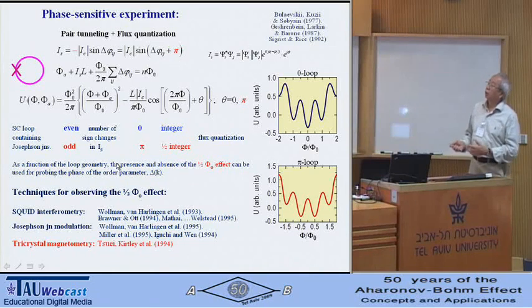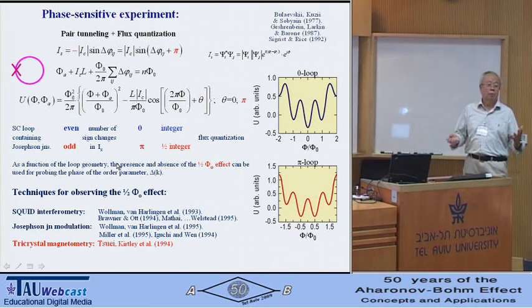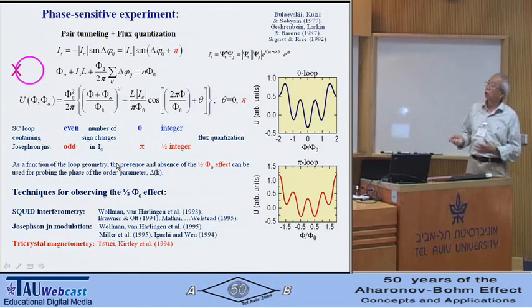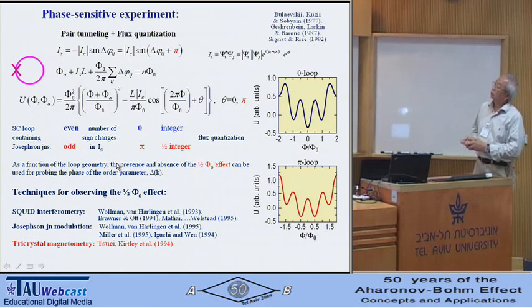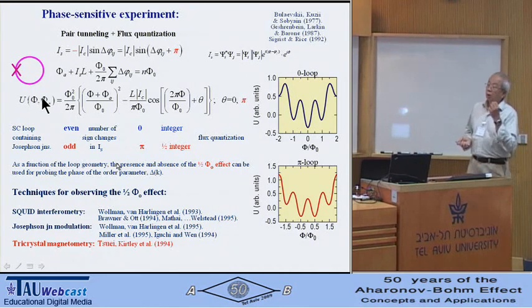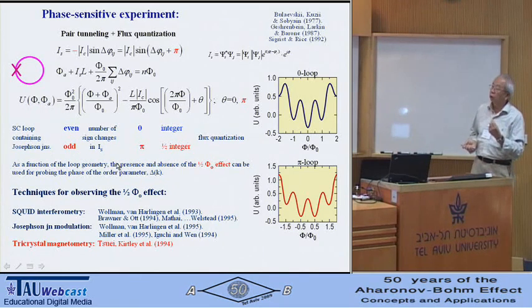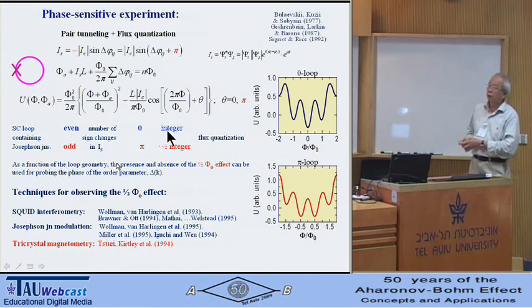phase shift. Now here is nothing more than the requirement of a macroscopic pair wave function to be single valued as you go around a loop of 2 pi. So when you calculate the energy, you work with a superconducting loop containing Josephson junctions. All you have to do is count the number of sign changes in the supercurrent. If it's an even number of sign changes, then you get a net phase of 0 or 2 pi. And that leads to regular integer flux quantization, as I indicated here.